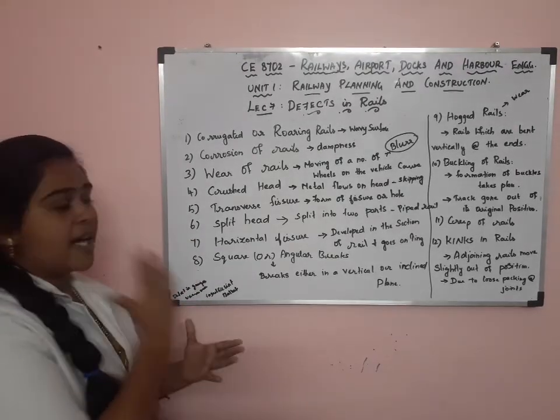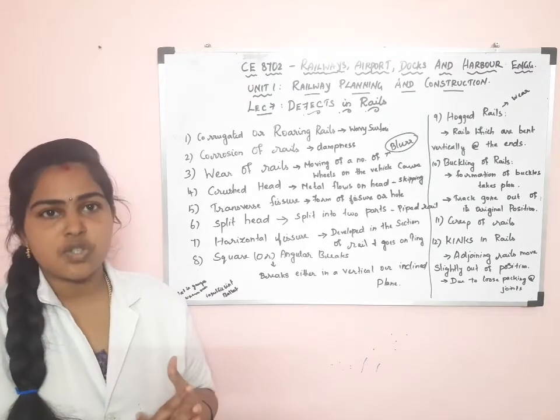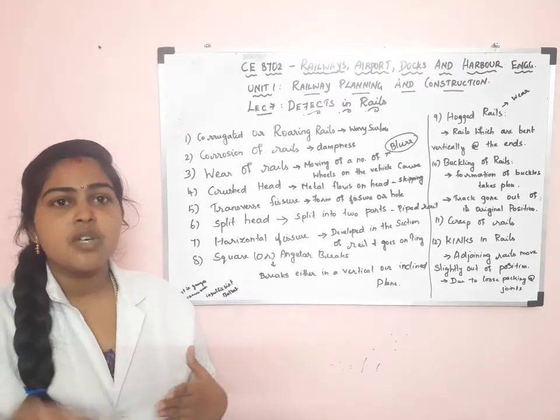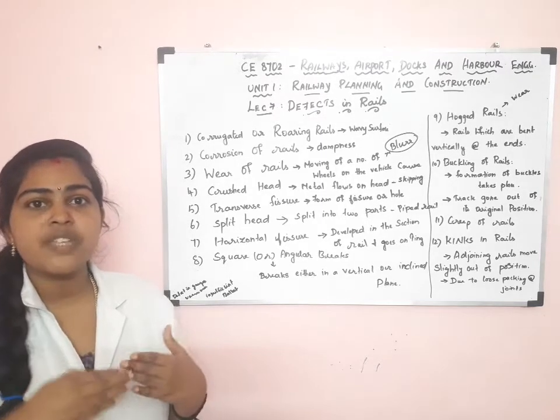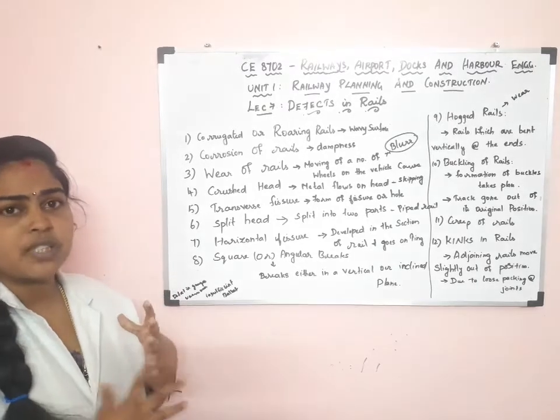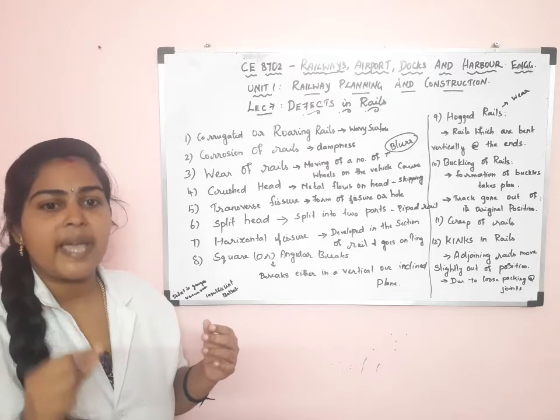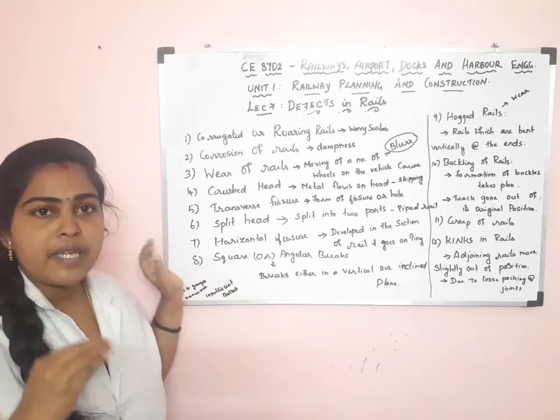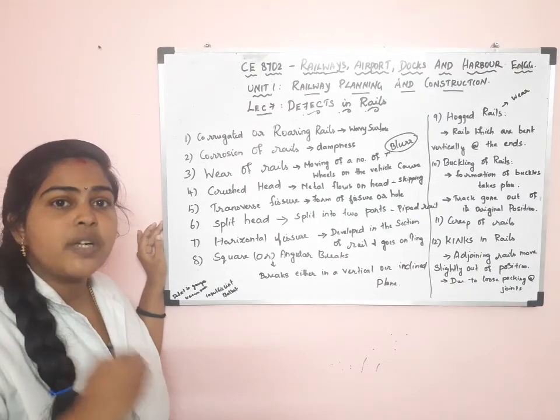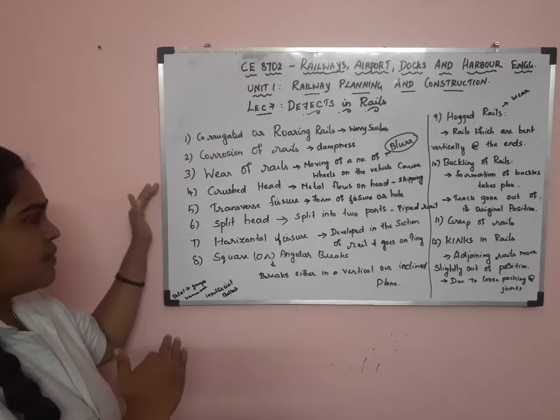To prevent corrosion of rails, we have to use quality rails — that is, special alloy steel should be used in the manufacture of rails. Otherwise, we have to give surface treatment, that is coating. We can coat with special paint, red lead, bitumen, coal tar, etc. In India, what is done is coating with zinc chromate on a priming coat of red lead, and after that, three coats of bitumen emulsion are applied. This is the surface treatment given where the rails are corroded.